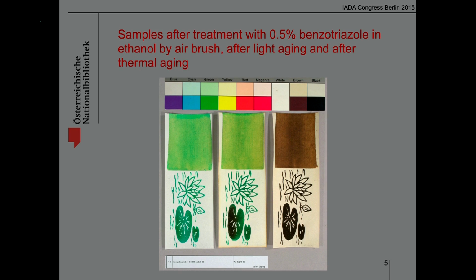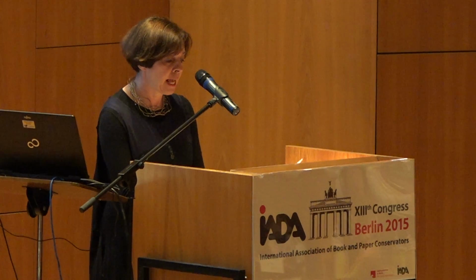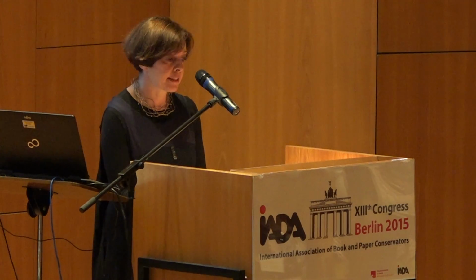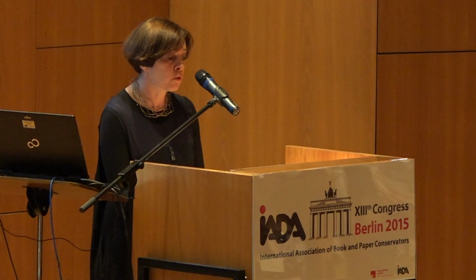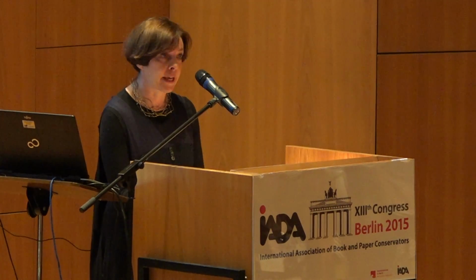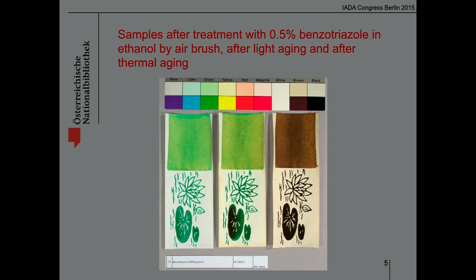In the research project, samples were prepared by applying copper acetate in gum arabic to handmade gelatin-sized paper in thick and thin layers of paint. The pre-aged samples were treated with different solutions of deacidification, antioxidant, and complexing agents. The treated samples were submitted to accelerated aging at 80% relative humidity and 65 degrees Celsius. An additional set of samples was light aged. In the slide on the screen, you see samples treated with a 0.5% solution of benzotriazole by airbrush on the suction table after treatment, then after light aging in the middle, and after thermal aging.